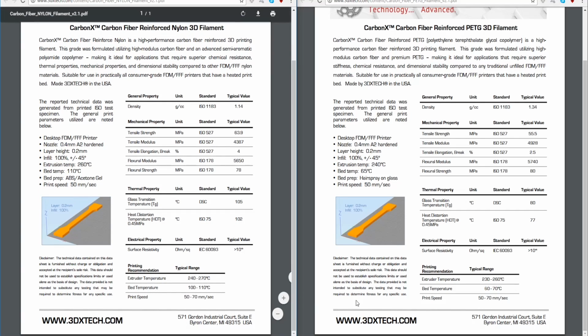Alright, so the carbon fiber nylon versus the carbon fiber PETG, I would probably still pick the carbon fiber nylon. It's got better tensile strength, almost as good stiffness, twice the elongation, almost the same bend, and a little bit lower flexural strength, but more temperature stability and more heat distortion under load stability. But slightly different as far as the printing range.